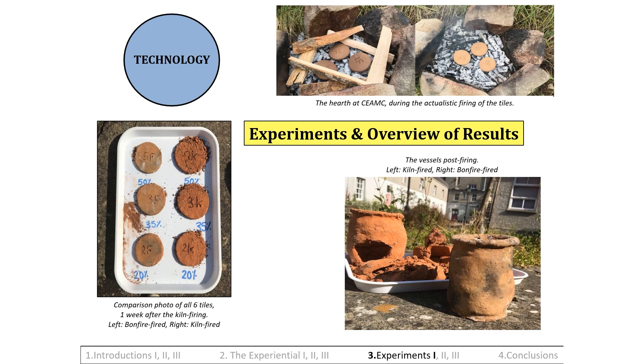The tiles were fired between 500 and 800 degrees Celsius, which infers that Trevisker ware can be fired at relatively low temperatures, and may explain prehistoric inclinations towards gabbroic clay usage. Ironically, three of the vessels were kiln fired in order to save time, but the kiln ended up causing more harm than good. Initial observations showed that the kiln ceramics had slaked. The cracking seemed to precipitate from the inclusions, which had turned black, likely due to chemical reactions undergone during the kiln firing process. The slaking continued until the entire collection crumbled entirely.